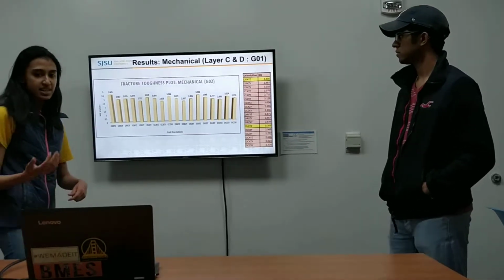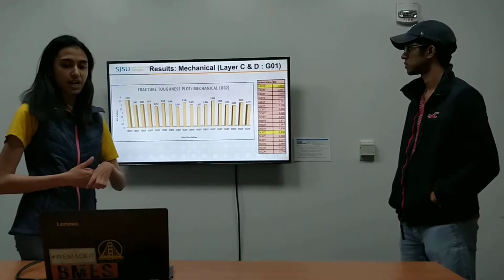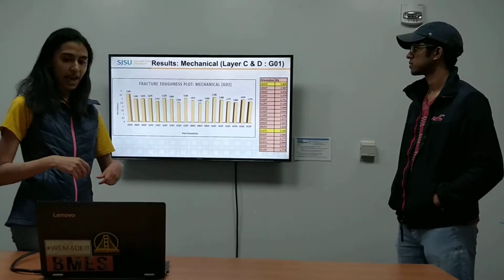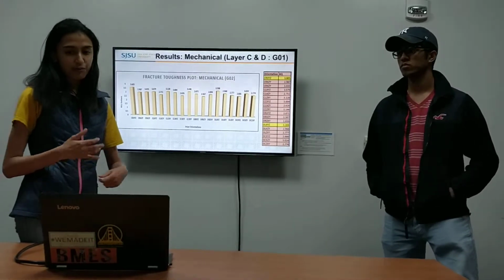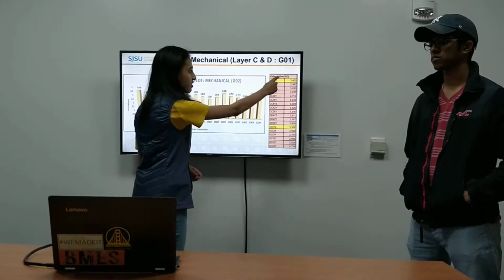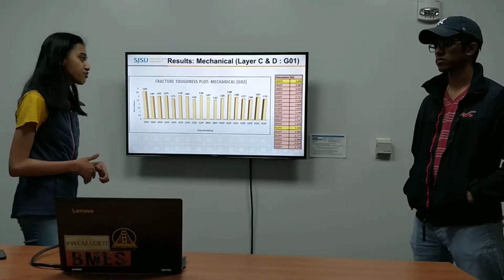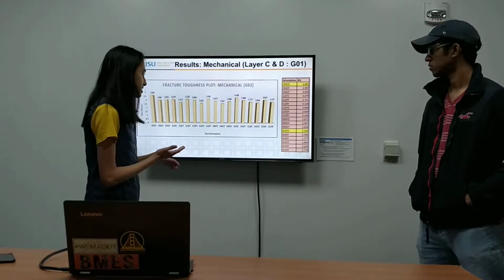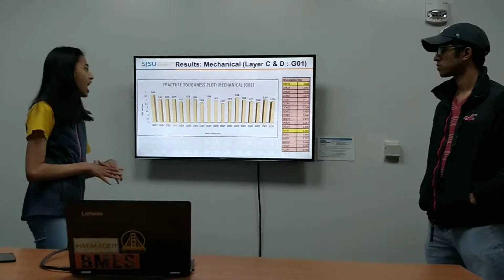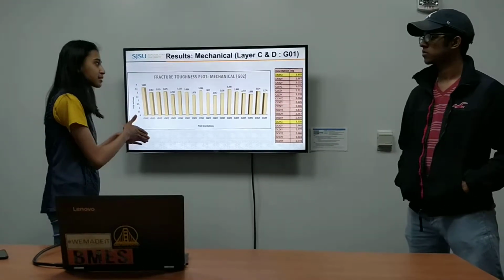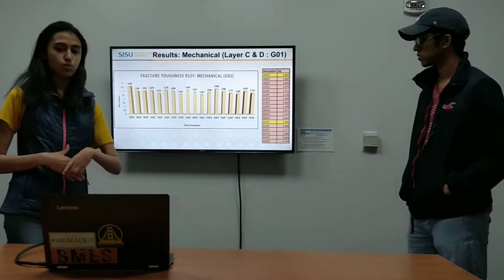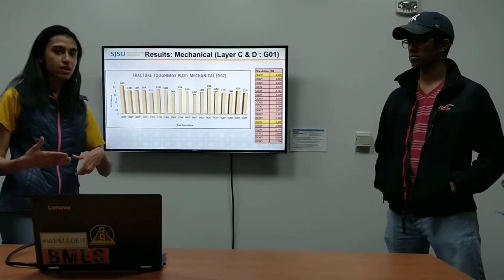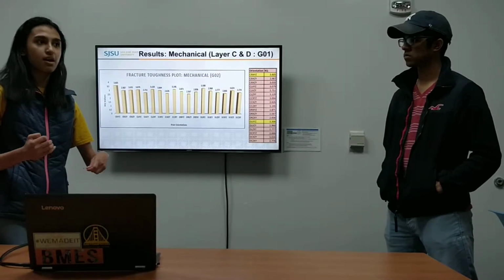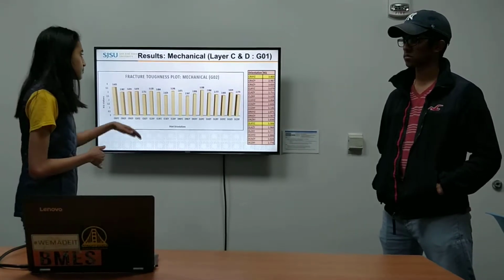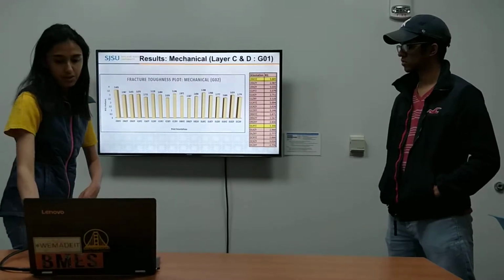In the same way, we produced bar charts for mechanical print settings for printer 2. And here we found that CL XYZ produced the highest fracture toughness, and DL XYZ produced higher fracture toughness for the D layer. So you can see how the mechanical print setting between printer 1 and printer 2 changes. So we found that printer 1 was better than printer 2 due to some technical problems with the parts of the printer.